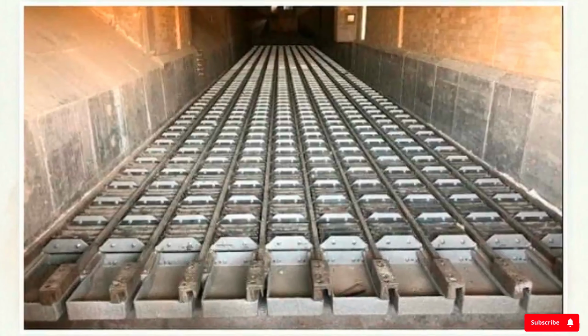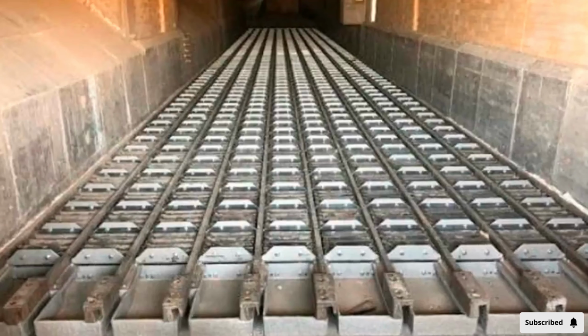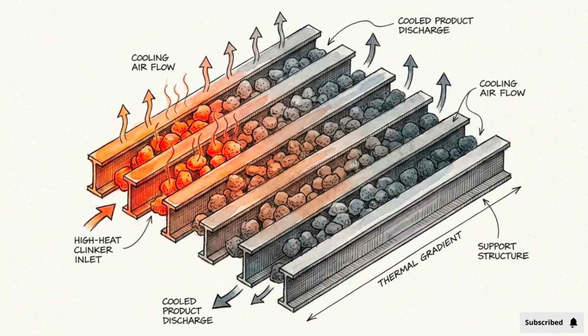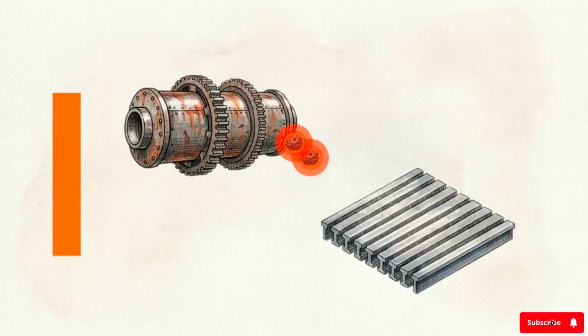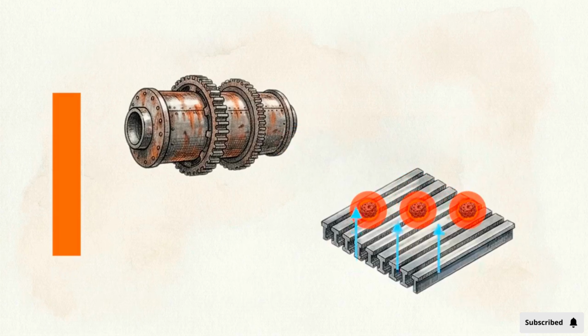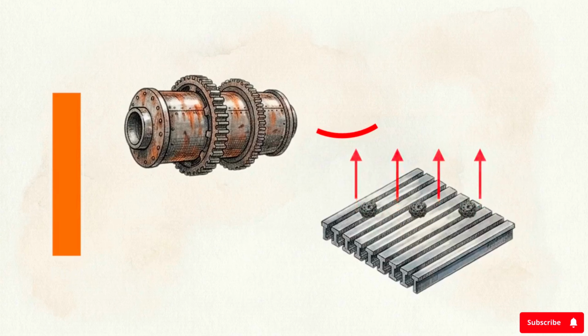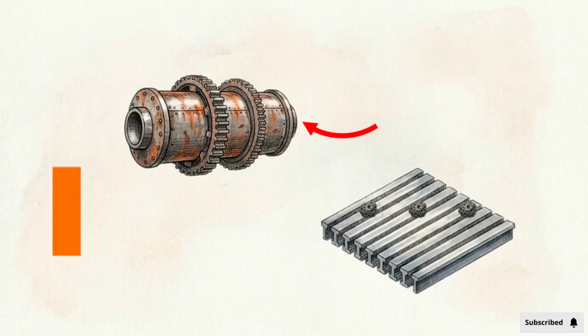Those nodules drop onto a series of parallel metal grates in the cooler. High-pressure fans blow cold air through the grates to rapidly drop the temperature of the material. This cooler is a critical part of the plant's efficiency. The air that chills the clinker absorbs its heat and is recycled back into the kiln as tertiary air, significantly reducing the amount of fuel needed for combustion.